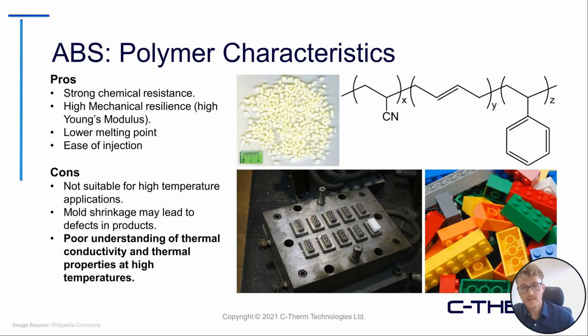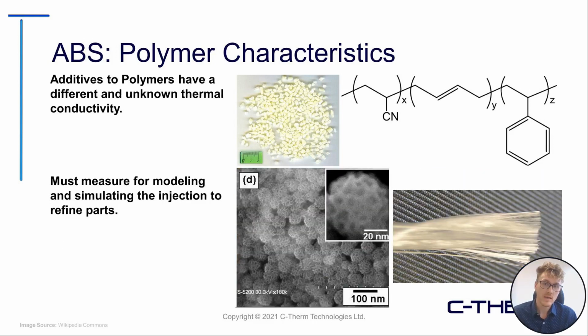So a good example of this is ABS, where ABS has a strong chemical resistivity, high mechanical resilience, low melting point, and has very good desirable characteristics for injection molding. But it's not suitable for high temperature, and mold shrinkage can lead to defects in the products. And this is due to the fact that there's a poor understanding of thermal conductivity of the ABS, or additionally of additives in these polymers, which will change the thermal conductivity.